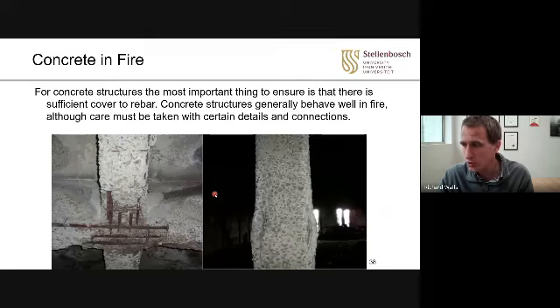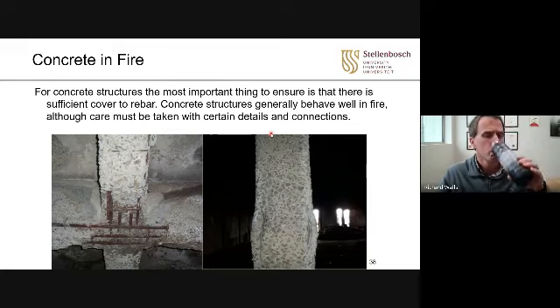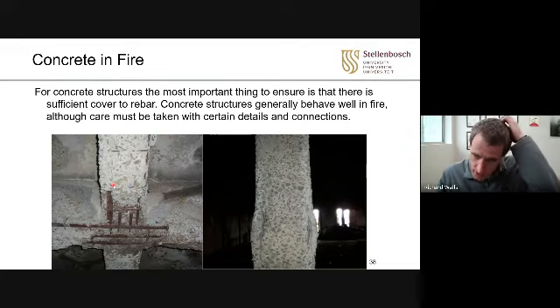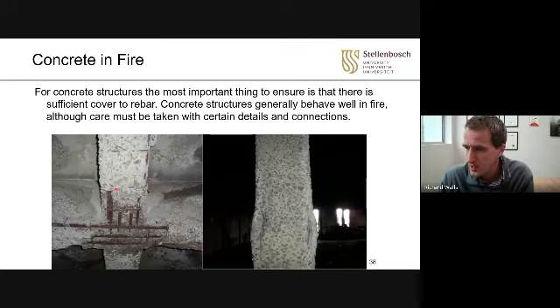In terms of concrete in fire, concrete typically does well. For most concrete structures, the most important thing is to ensure that there is sufficient cover to rebar. Concrete structures generally behave well in fire, although care must be taken with certain details. So here you have a structure. This was in a project I was involved with, very, very severe fire. All the concrete popped off, rebar was exposed, severe damage. This had to be demolished. You can actually see this column here is starting to buckle, that it's actually popping out on the side.